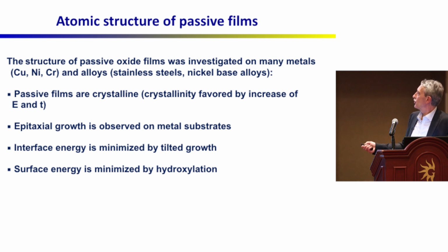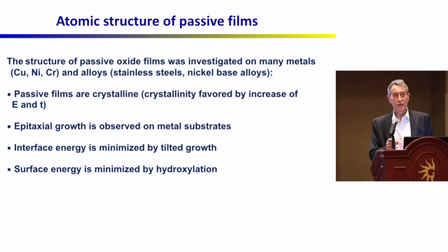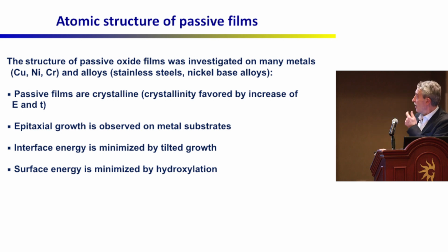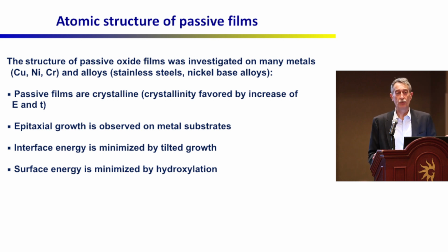And this minimization is done by a tilt in the direction of growth of the oxide with respect to the metal. And that, of course, you can observe only if you control the structure of both the surface and the oxide. And the surface energy is minimized by hydroxylation, and to know that you have to use methods like XPS, for example, that will tell you how many hydroxyls you have on the surface.